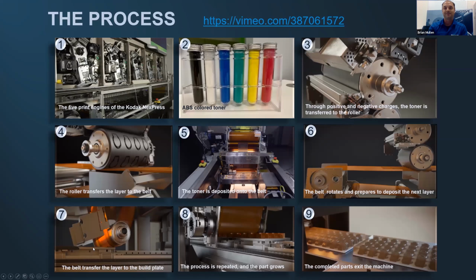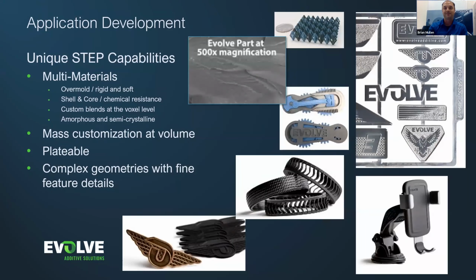So the image comes on top of our part build, and you can see in step eight, we have a certain Z height that builds up after we have transferred so many images over and over until we finish the build. And so you can see the parts, at least with this cartoon, within this build. However, most of our materials are black or blue in nature. And so it might be difficult to see them in the final build. Our final builds look like a pretty large rectangle. And then after the rectangle is put into a post-processing machine, the parts come out and we analyze them. These are some of the parts.